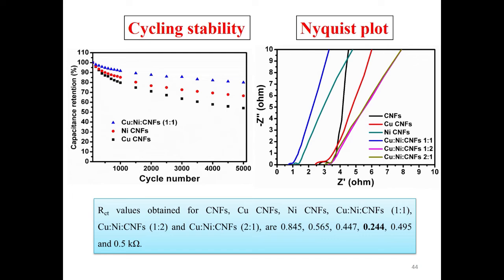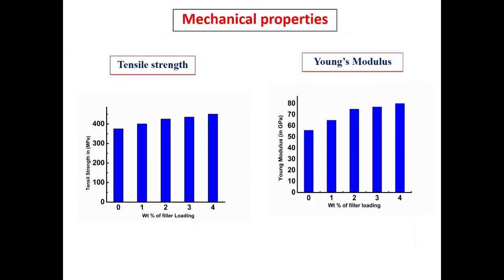Cyclic stability and Nyquist plot: 1:1 is found to be very effective compared to the others. This is the tensile strength and Young's modulus. Here 4 weight% shows high tensile strength as well as Young's modulus compared to 0, 1, 2, 3 weight% loading of the filler. The purpose of this study is to verify the strength of the material, because high strength supercapacitors are chosen for this application. The improved tensile strength and Young's modulus show that this material is very effective for the preparation of the supercapacitor.